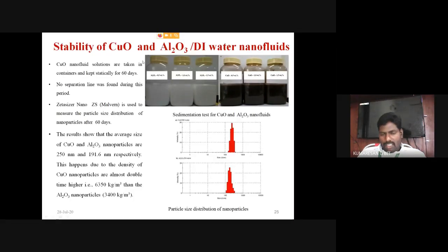Okay, this prepared nanofluid is kept statically for a duration of 60 days. During this period, no separation line was found, irrespective of the mass concentration. Then the Nano ZS device is used to measure the particle size distribution of the nanoparticles after the experimentation was conducted. Then during this test, the size of the nanoparticles was found to be nearly 250 nm and 191.6 nm for the copper oxide and aluminum oxide.